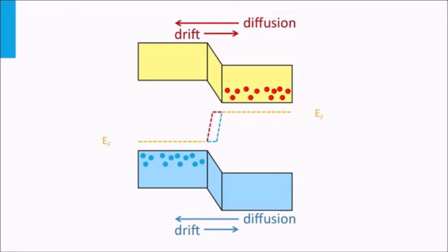The p-n junction is not in equilibrium anymore, and this results in a splitting of the Fermi level in the depletion zone, which are called quasi-Fermi levels. The upper level represents the population of electrons, and the lower level represents the population of holes. In equilibrium, these distributions are mirrored and related by the Fermi-Dirac function as discussed in block 2.4.